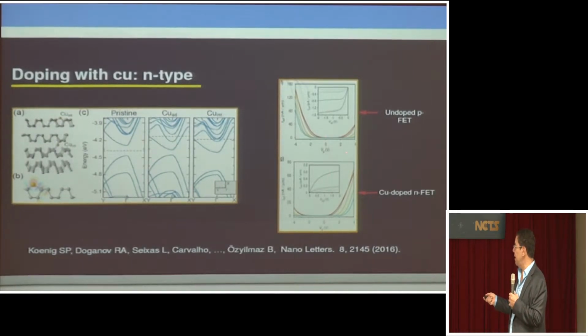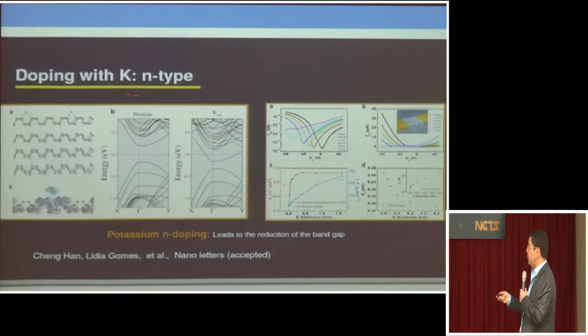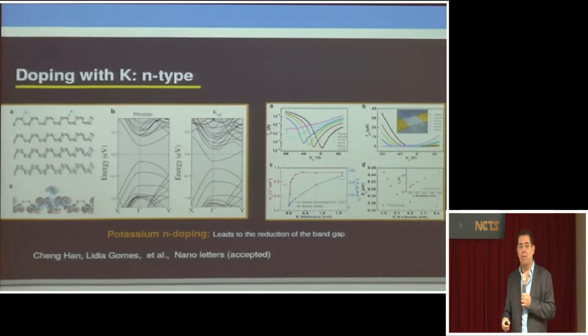Okay? Actually, this is experimental data, without copper and with copper, and you can see this is the IDV, the current versus voltage, and you can see a shift of the IDV and a shrink of the band gap in the system, in agreement with band structure calculations. So it's very good that we can explain these things with very simple calculations like that. But it's not always the case. So this is with potassium, again an alkali metal. You dope these materials with potassium, and again it donates electrons, and you change the size of the gap. And again, these are experiments that you can do in the lab, and you can test the predictions of the theory, and everything works out very well for this type of material, phosphorene.